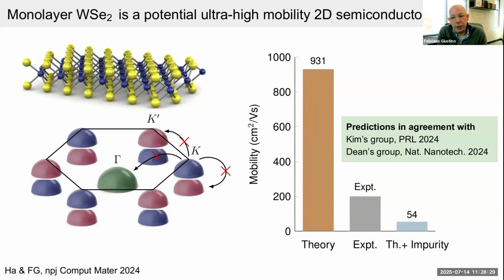So the main message here was that if you perform calculations in the pure sample, you get some extraordinarily high values of mobility. And as soon as you incorporate impurities, this drops down to very poor mobilities. So the message is actually that if you want to achieve high mobility, one should focus on this material and on making it as pure as possible. And this is not just a fantasy. Actually, last year, at the same time as when we made these predictions, the groups of Phil Kim at Harvard and Cory Dean at Columbia managed to synthesize tungsten diselenide with an impurity content of less than 10 to the 10 per centimeter squared.